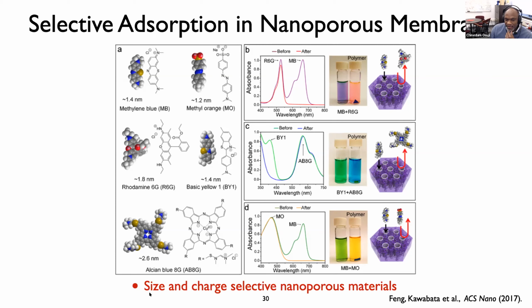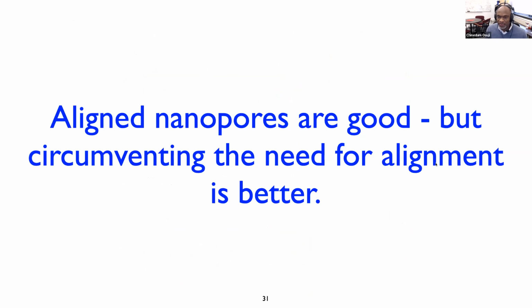So we can get very, very highly selective membranes based on size and charge, and this was tested just in adsorption, right, not in pressure-driven flow. So aligned nanopores are good, and essentially what we chased after initially was the creation of membranes in the way that my 7-year-old daughter might envision them: a thin film with lots of holes in the film, with the holes all the same size and aligned in the same direction.